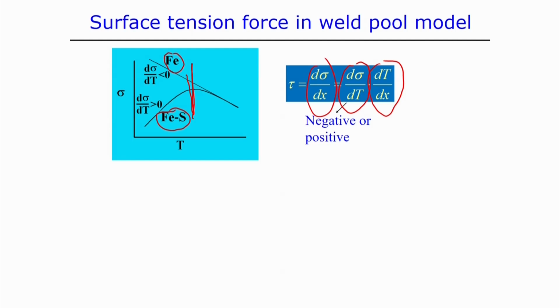The temperature coefficient of the surface tension force can be negative or positive depending upon the presence of surface active elements. For example, in the case of a pure system, it becomes negative. If it has surface active elements, that slope becomes positive. The second component is the temperature gradient, which is always negative, because at the center point of the weld pool the temperature is the maximum, and at the outward periphery and the boundary the temperature becomes less. So, the temperature gradient is always negative in this case.